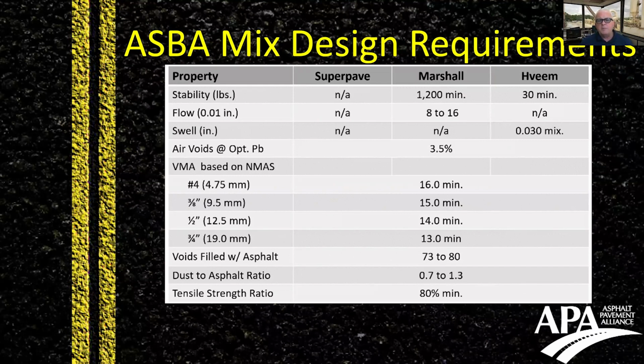These are Marshall mixes based on the specification that I looked up, and there's a VMA requirement. Essentially, it's just saying we want this to be a healthy mix. It's a 3.5% air voids mix, has a Marshall stability and flow requirement. It even has a TSR requirement on it to make sure that it's got good resistance to moisture damage.